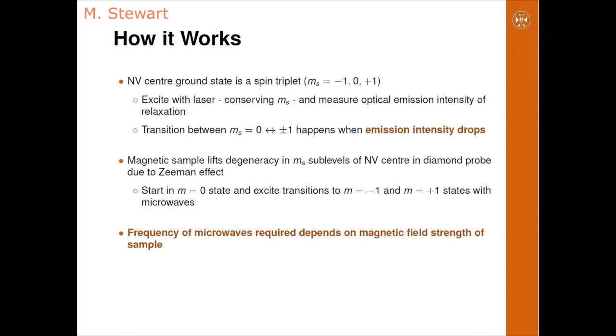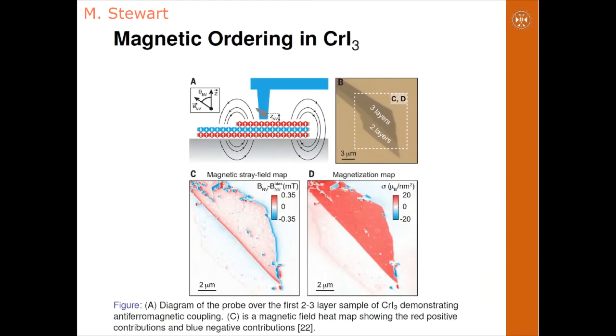With the probe over a magnetic sample, the energies of the ms sublevels are split by the Zeeman effect. Now, we can excite a transition from ms equals 0 to -1 or +1 with microwaves. And so if we can find the frequency of microwaves where we see an intensity drop in the optical emission, this indicates a change in ms and tells us the energy of the splitting, and hence the magnetic field at that point in space where the probe is. Here's a recent example of NV center magnetometry utilized in an atomic force microscopy setup to investigate a few layers of chromium triiodide. They found antiferromagnetic layering by mapping out the magnetic field, shown in the bottom left.